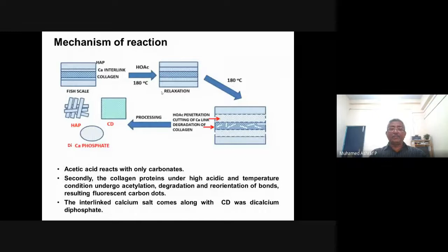And then what is the real mechanism that occurs when we treat the fish scale with acetic acid? When we introduce acetic acid in the hydrothermal reactor, acetic acid selectively reacts with the calcium derivatives. For example, there is an interlink between calcium, collagen interlink is there, and then hydroxyapatite is there.